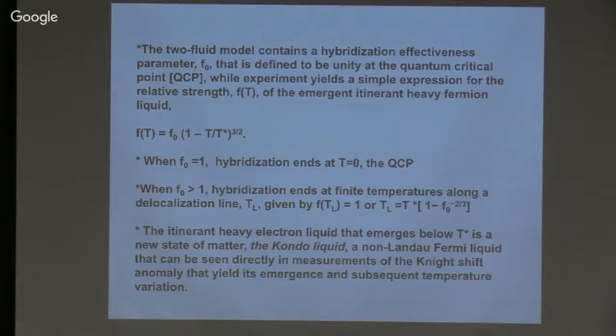F equal 1 is the end of local moment behavior. The strength of the local moment part is proportional to 1 minus F. So F equal 1 marks the end of local moment behavior. And that says that F naught is a good tuning parameter. F naught equal 1 is the quantum critical point. If F naught is less than 1, you can say this is a weakly hybridizing system. If F naught is greater than 1, it's a strongly hybridizing system.